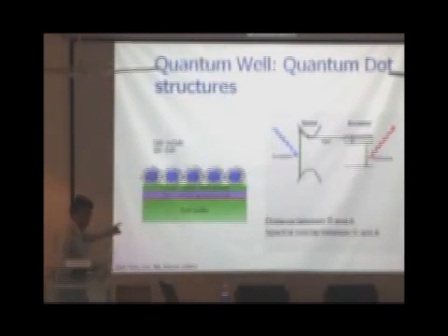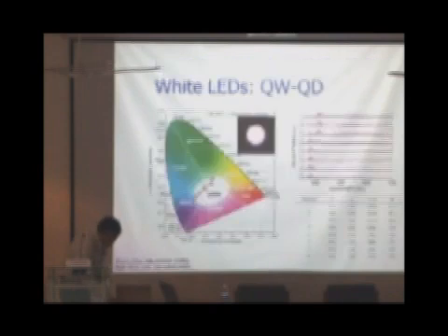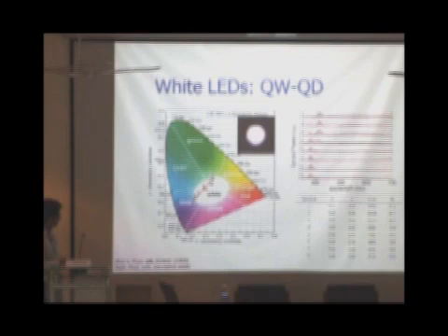Okay. One of the light emitting devices we made was something like that. Indium gallium nitride, UV light emitting diode, and on top of that we put our cadmium sulfide. So it basically Förster energy transfer, which is giving an excitation to the cadmium sulfide, which has a lot of surface states, and it's going to emit white light. So that's a real working device over there. And this was the one that I showed you in the very beginning as a glimpse.